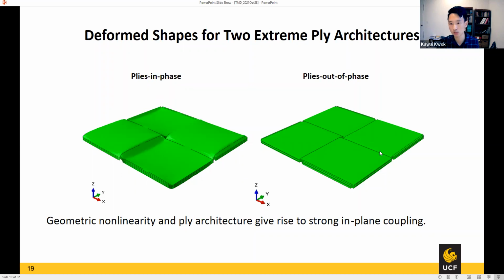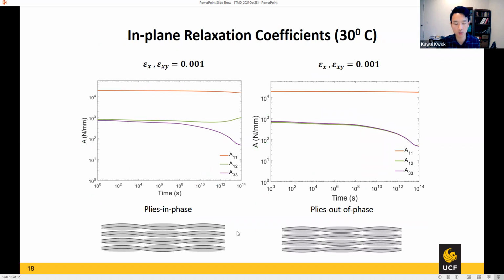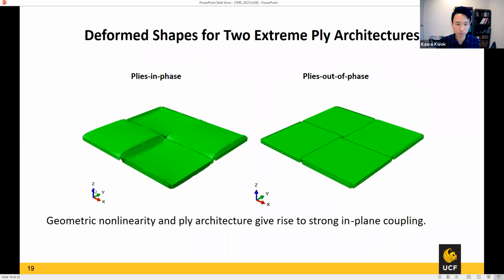But if you do that on the out-of-phase configuration laminate, that does not happen, because they exactly cancel out. As you go along the thickness, in each ply that geometric nonlinearity effect is canceled out, so it's still a flat laminate. So it's really the out-of-phase configuration that is actually the symmetric one, even though the plies are all the same in the in-phase configuration. If you look at an axis in the middle, you don't actually get a mirror symmetry. Because of that, you get a much stronger coupling in in-plane stretching.